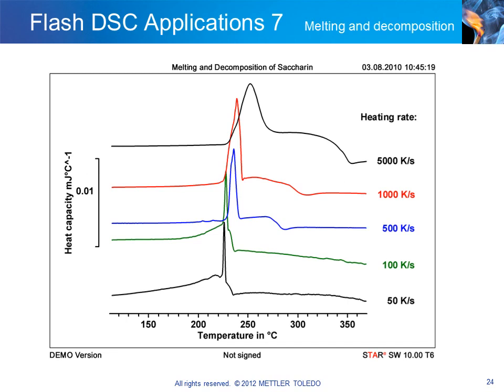The temperature at which kinetic processes take place can be shifted at higher heating rates. An example is the overlap of melting and decomposition, which occurs in many organic materials. Saccharin is shown here as an example. At lower heating rates, decomposition begins before the melting peak. At higher heating rates, decomposition is shifted to higher temperatures.